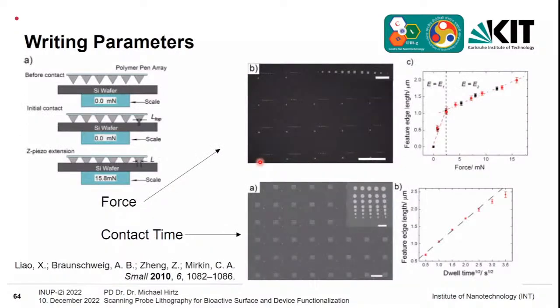So also here we have different writing parameters. One is the force and one is the contact time again. Now here we have force also as an additional writing parameter, because if you press more and more, you will deform the tips, because now they are flexible. Like I said, it's an elastomer like PDMS. And this leads to bigger and bigger features the more you press, because you simply press harder onto the surface.